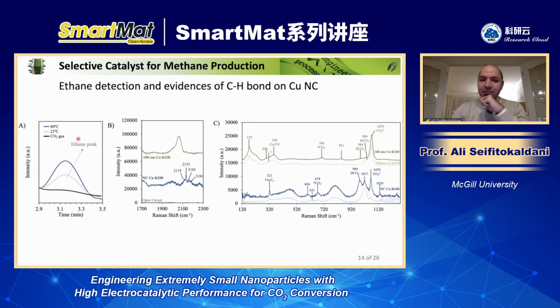And also by increasing the temperature, we observed that the amount of ethane released also increased for the same reaction condition. By reaction condition, I mean same electrolyte, same flow rate for the gas, same temperature, applied potential, same current density. The only difference was we just heated up the electrolyte a little bit, so we got a higher temperature, which enables the ethane to leave the surface much easier. But then there was absolutely no peak on larger particles, like 100 nanometer or 200 nanometer. So kind of supporting our hypothesis that the small particles are able to adsorb ethylene strongly and then convert it to ethane to leave the surface.